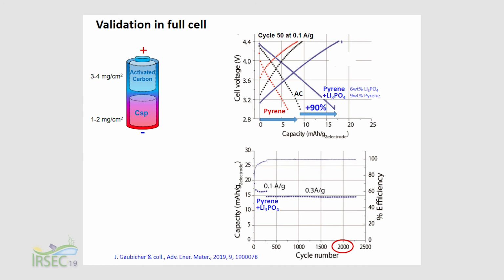You can see that at cycle 50 we still have almost double capacity for the system containing the two additives in the positive electrode compared to only activated carbon in the positive electrode. We have done also long-term cycling, and we find that we get constant capacity over several thousand cycles, and we get Coulombic efficiency close to 100%. So this shows the robustness and the efficiency of our new concept.